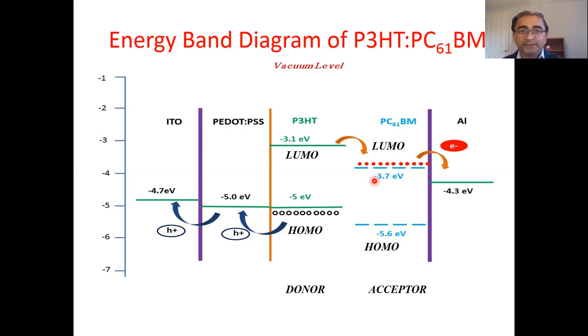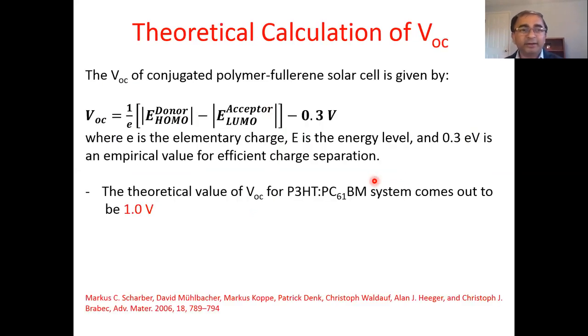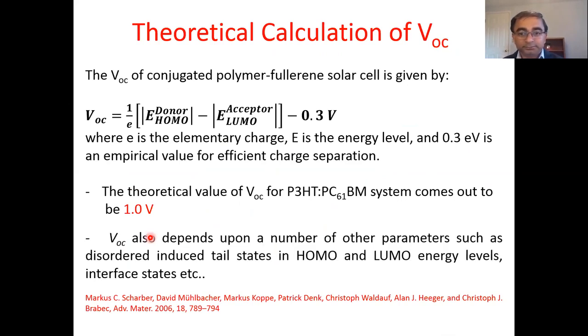Now, this is some sort of theoretical calculation of how these HOMO-LUMO levels are related to the VOC of that material. And for P3HT, the highest theoretical value is 1 volt, but it's difficult to achieve because of different reasons, because of impurities and other reasons, such as disorder-induced tail states, HOMO-LUMO energy level, interfacial states, and all that. This is all due to defects, and it will decrease your VOC from the theoretical value to a practical value.